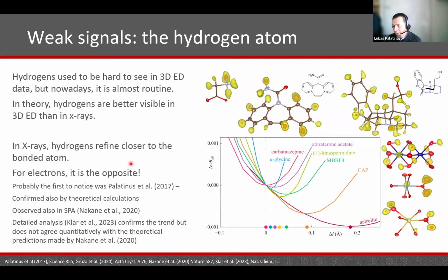But there is an interesting aspect to be aware of when refining hydrogen atom positions from electron diffraction. You probably know that in X-rays, if you freely refine hydrogen position, it will refine to a distance to its parent atom or bound atom, carbon, nitrogen, or oxygen, that's significantly shorter than the nucleus distance by about, say, 0.1 angstroms. For neutrons, if you do neutron refinement, then the distance will be the right nucleus distance, because neutrons are sensitive only to the nuclear positions.